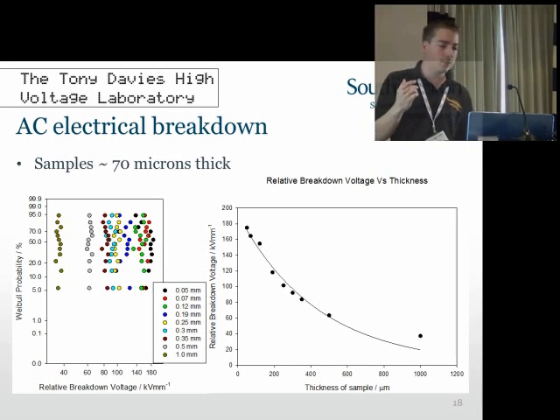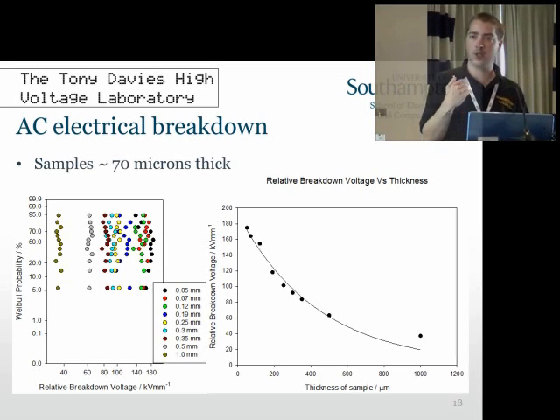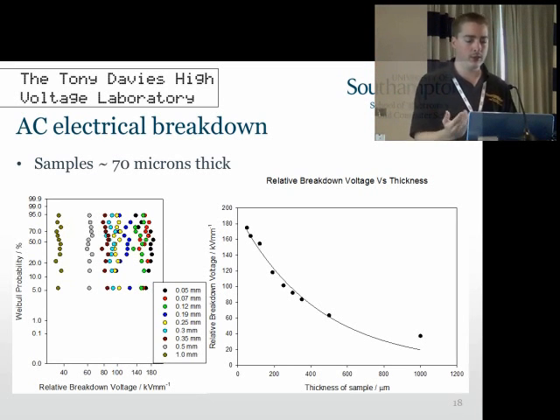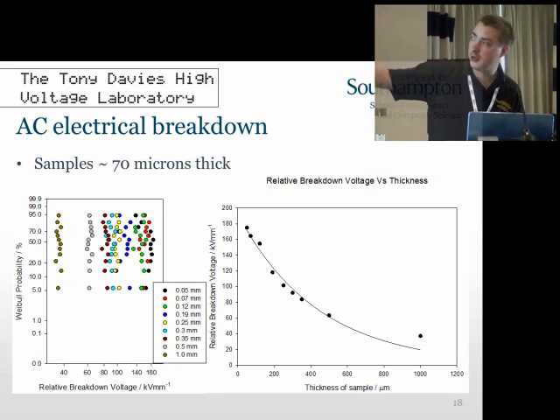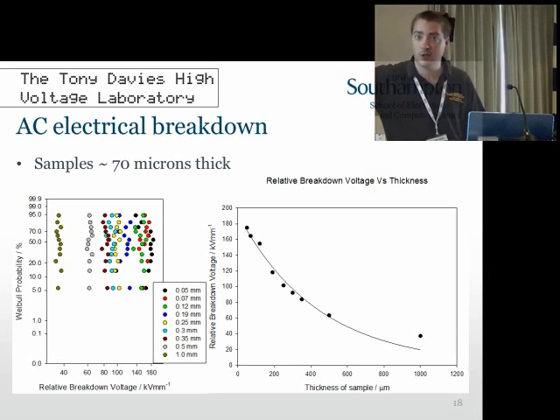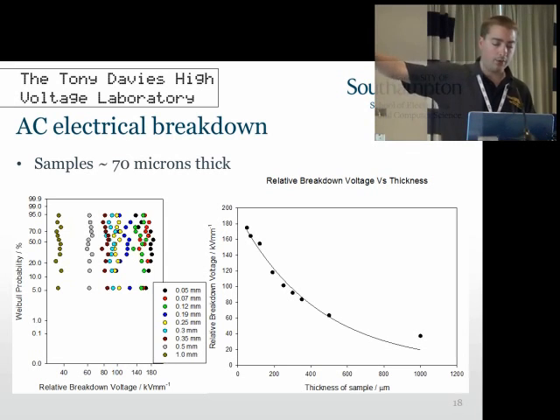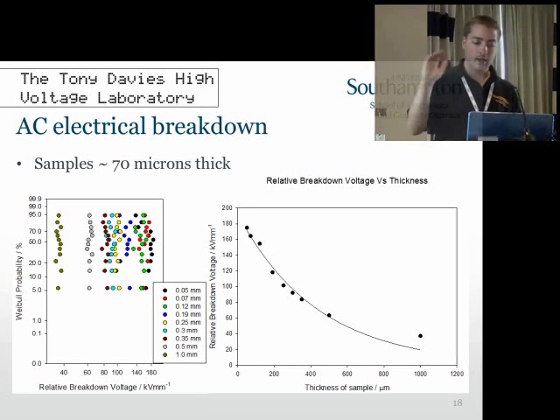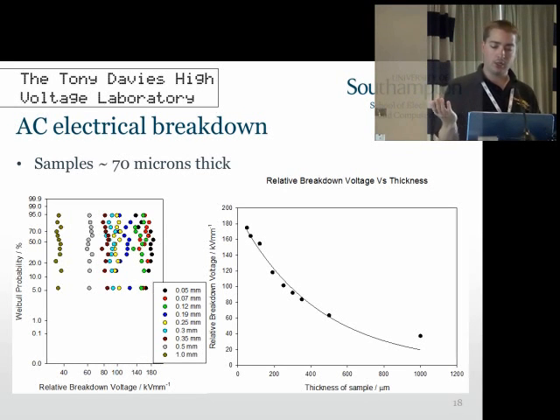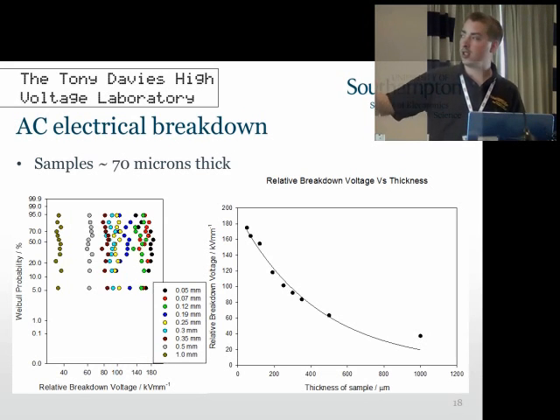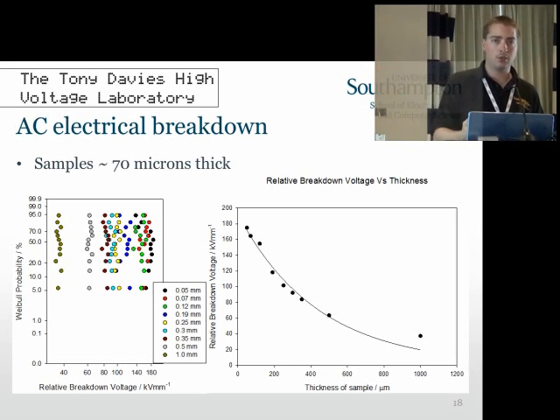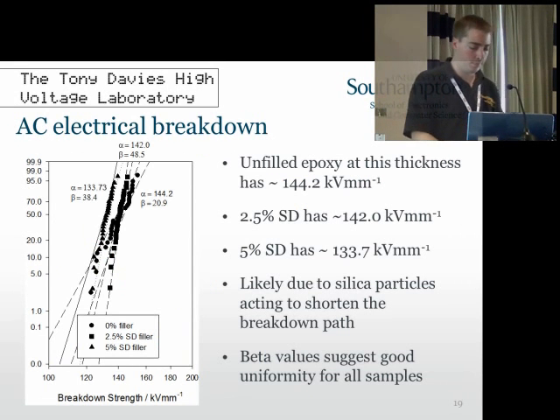So if you have a sample that's 70 microns and you want to compare it to something that's 90, you have to take this relationship into consideration. Okay. The left-hand graph there just shows the same. This is alpha value, sorry, from a Weibull distribution. The Weibull distribution is shown on the left. And as you can see, the breakdown strength still decreases as we increase the thickness. So this was just a basic study of our epoxy, just so that if we couldn't produce samples of the same thickness to test, we knew the relationship that would align them all.